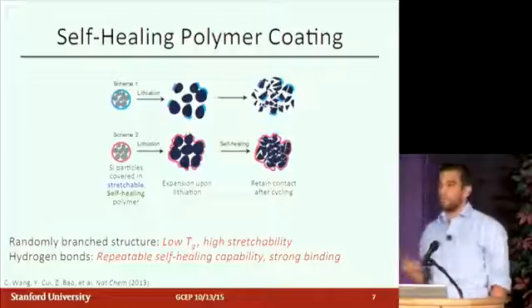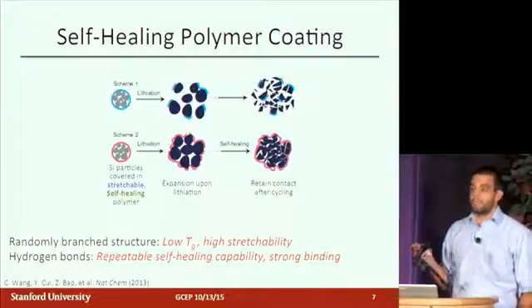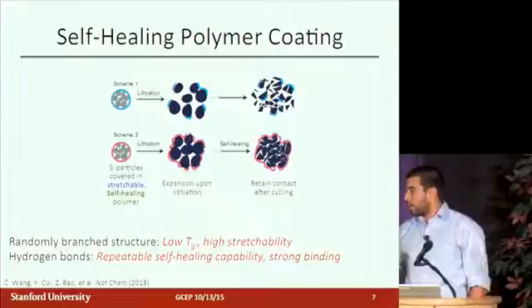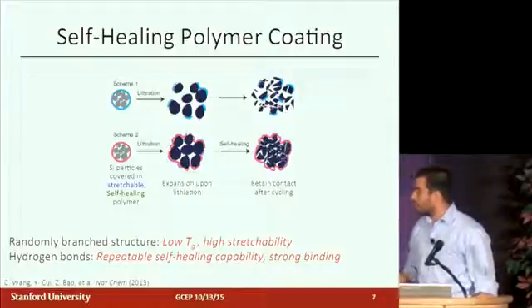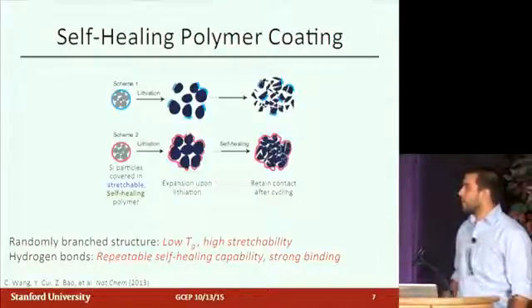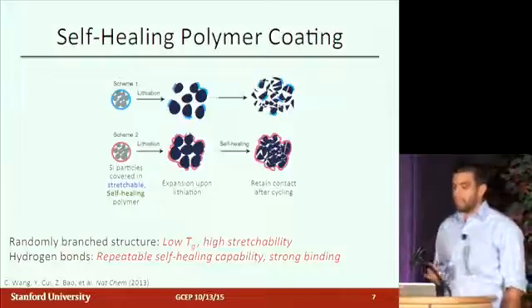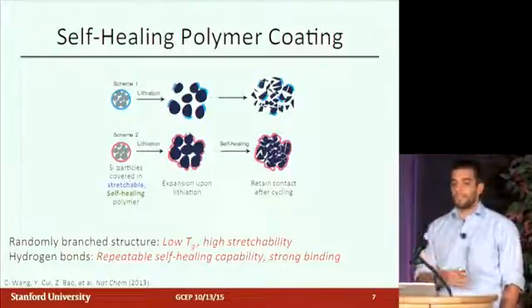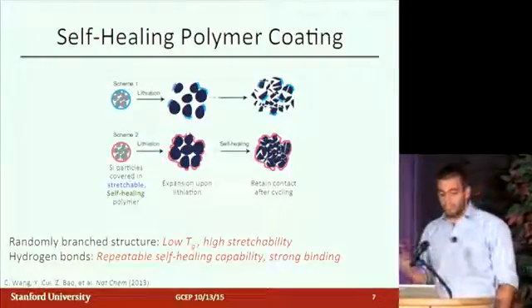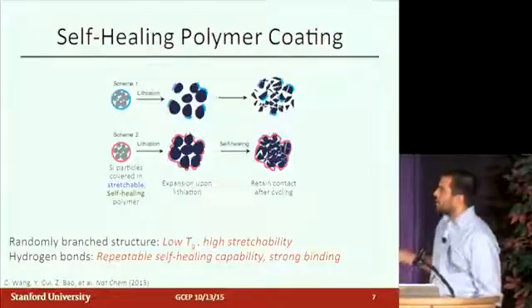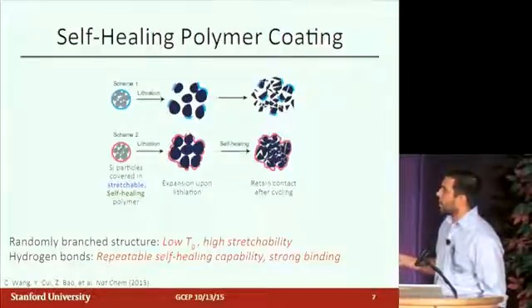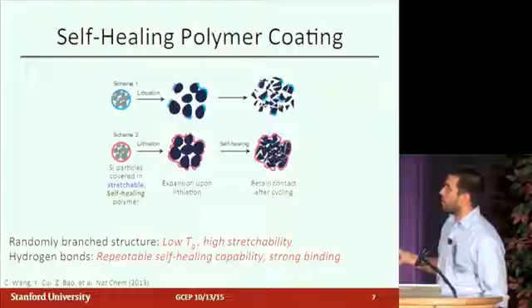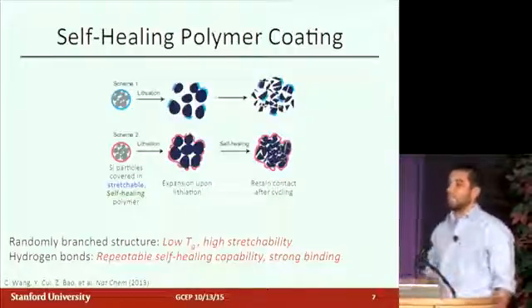What we do, and what I'll be talking about today, is a self-healing polymer coating. And it's a concept that Chao, a postdoc in our group, published back in 2013. And how we think it works, we're still doing some in operando studies up at SLAC to really elucidate the mechanism. But what we understand right now is that in a traditional binder, you'll have large silicon particles that'll lithiate, and then after many cycles, they'll fracture, and your electrode will fail.